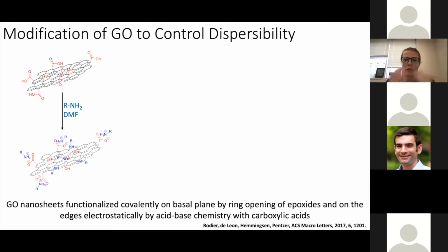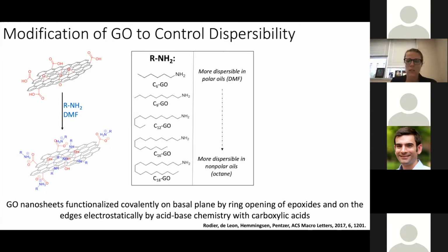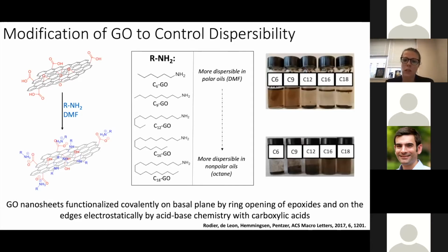And we do know that both of these reaction pathways occur from XPS. We can see in the nitrogen binding energy that we have both electrostatic and covalent modification. And so the idea was, if we have shorter chain alkylamine modified nanosheets, they're going to be more dispersible in polar oils, such as DMF or acetonitrile. Then if we use longer chain alkylamine to modify the GO, the nanosheets would then be more dispersible in octane. And Brad was able to show that he could indeed control the dispersibility of the nanosheets based on the length of the alkyl chain that's used.